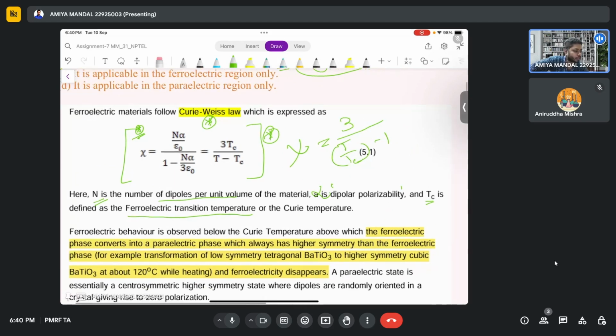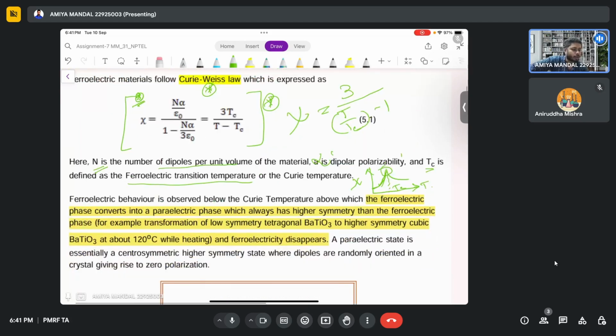If you see the variation of chi, you see that there is a certain jump at a particular temperature, that is Tc. So this is the ferroelectric transition temperature. It varies inversely proportional, meaning with temperature increment it varies at T greater than Tc. Ferroelectric behavior is observed below the Curie temperature Tc, and the ferroelectric phase converts into a paraelectric phase at T greater than Tc. The paraelectric phase has higher symmetry than the ferroelectric phase.